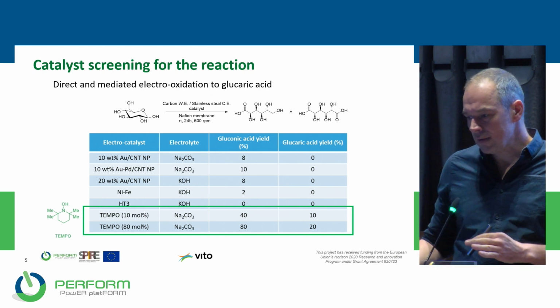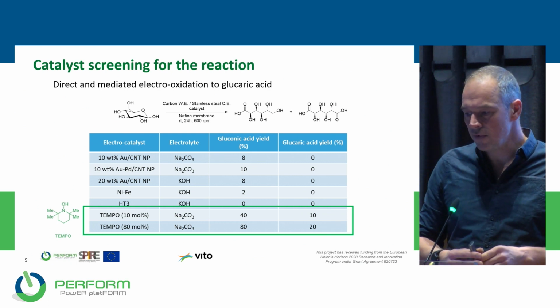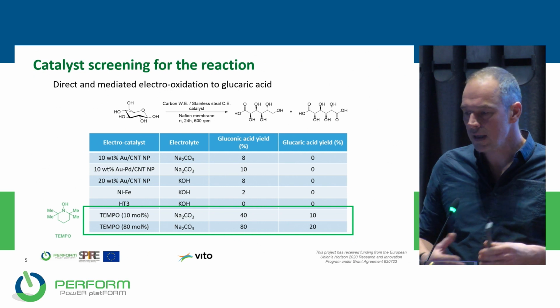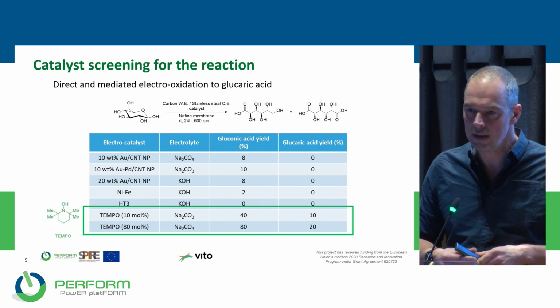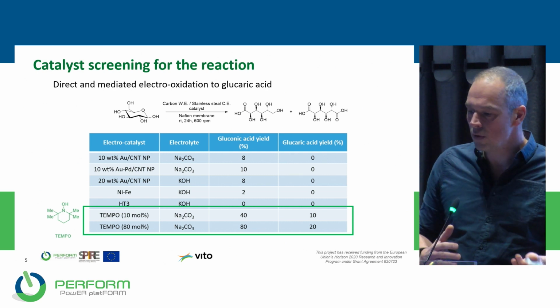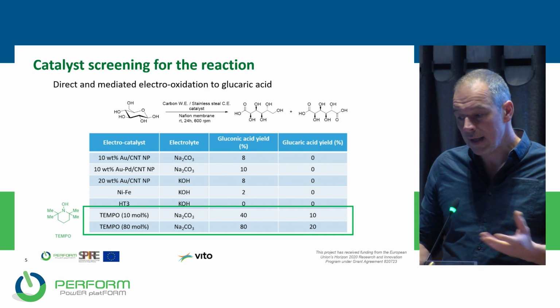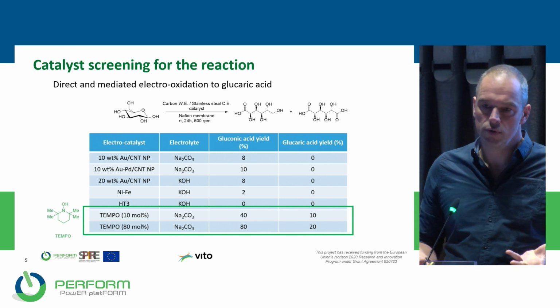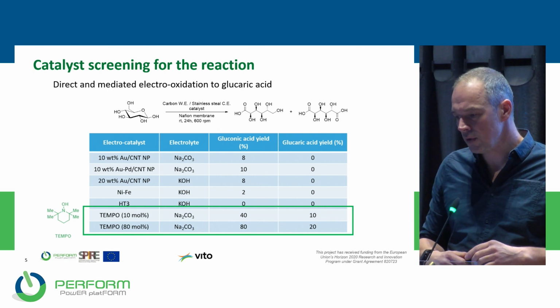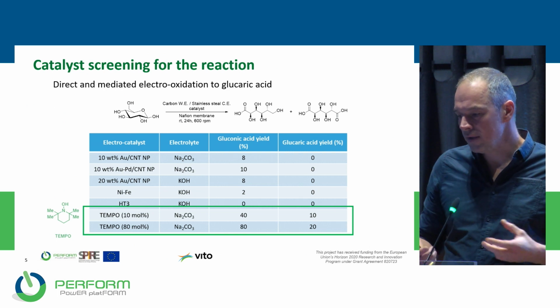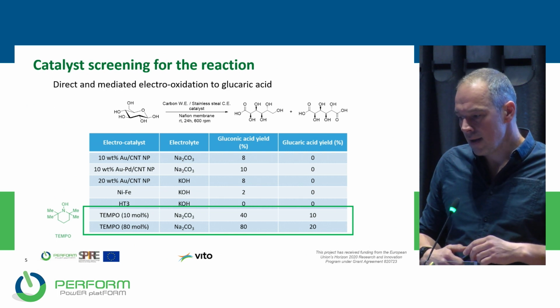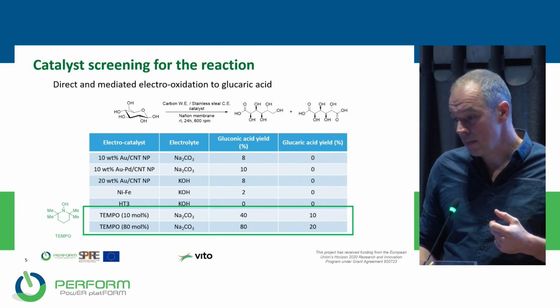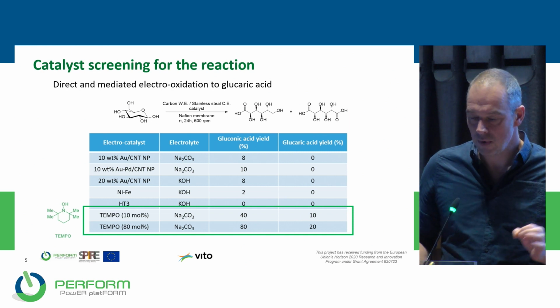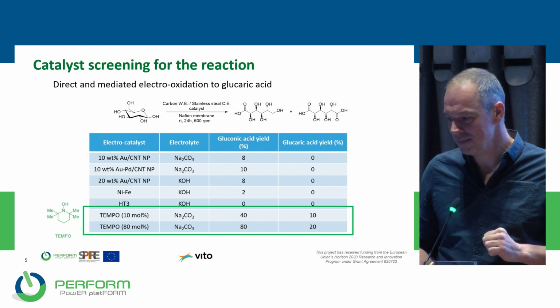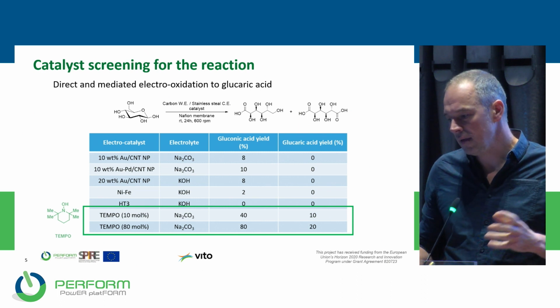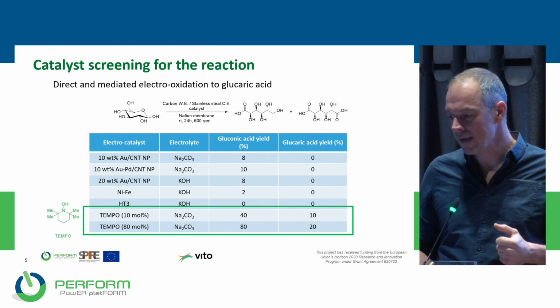So first of all, for the glucose to glucaric acid conversion electrocatalytically, we investigated several routes of direct electrooxidation using either gold, palladium, or nickel-iron catalysts, which were coated on particles, mostly carbon nanotubes, where nanoparticles of either gold or palladium were coated on. But in fact, these tests, which were basically done in H cells, so very small scale, square millimeter size, yielded only a few percent of gluconic acid, and actually no glucaric acid was found.